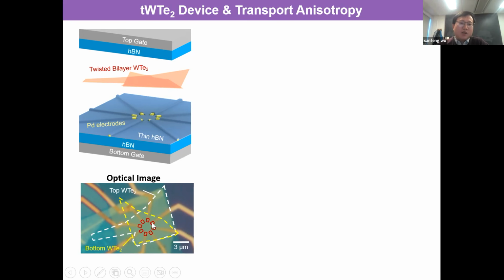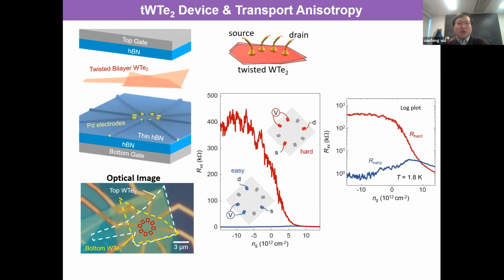What we really want to do is to put contacts only to the middle of the twist part in the ring structure so that we can study the anisotropy. So what we want to do is something like this. From source to drain, we pass current. We may want to measure voltage from other probes and so on. Once we make this kind of device, it's very robustly reproducible, or very easy to find, that the transport along different directions is very different.